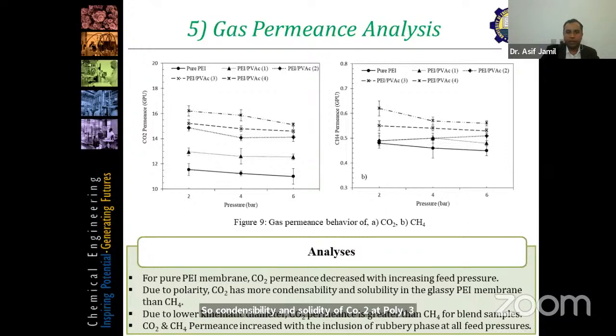And the other factor is the diffusion factor. For example, the CO2 kinetic diameter is very low, around 3.3 angstroms compared to CH4, which has 3.8. So because of the smaller size of CO2 molecules, they can penetrate and pass through the membranes quickly compared to CH4. So that's why CO2 permeance is higher compared to CH4.